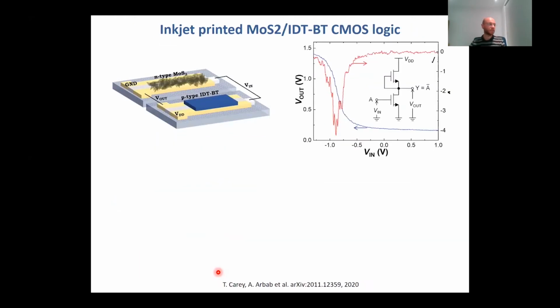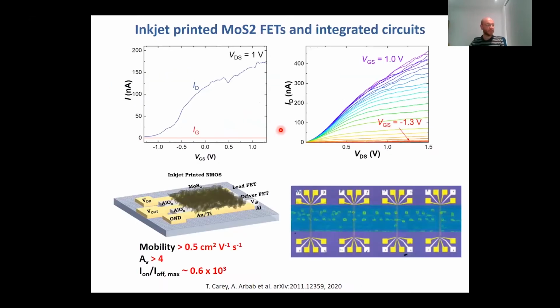and wearable devices. And here you can see, for example, the inverter working, a fully printed inverter, interconnecting two MoS2 devices, giving us a gain of around 4, which is, of course, way better than what we were getting with graphene. So we can definitely amplify the signal.